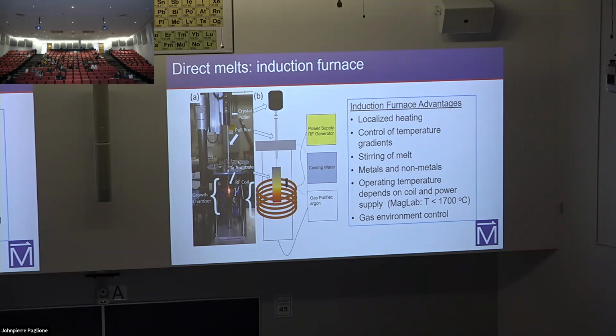But you've already run into a limitation, and that is that the quartz tubes that you're probably going to want to use start to soften around 1200. And I should say you can buy an even fancier furnace at higher temperatures, but it's going to break all the time. So this is one way to get around a lot of these problems because you can access these sorts of temperatures and you can create sort of arbitrary environments to contain them.